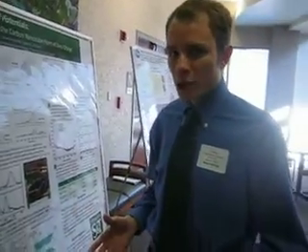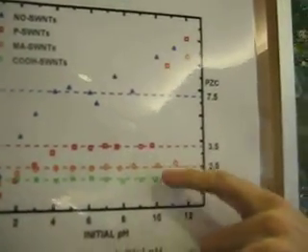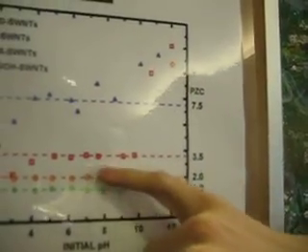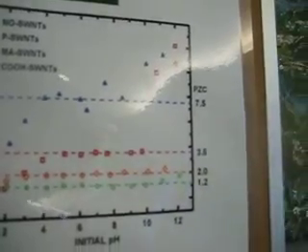After we had performed all these functionalization experiments, we also performed measurements of the point of zero charge of these samples. This is actually a pretty simple measurement to make because you can make solutions of various pH, measure their pH, add a single-walled nanotube sample to the solution, wait for several hours, and then make a final pH measurement. When you plot these, you develop a plateau in the region, which is representative of an equilibrium that the ions try to reach with the nanotube surface. This plateau region indicates the point of zero charge of the sample.